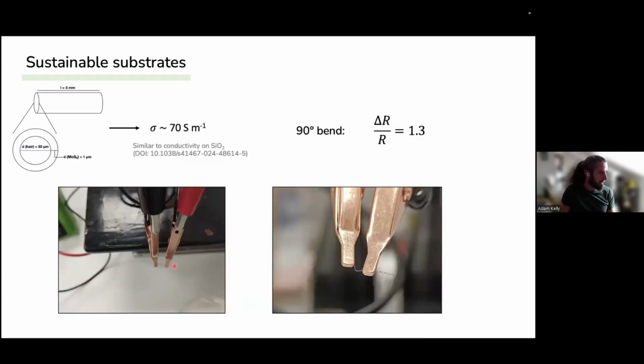So we coated one of these hairs. We calculated then the conductivity of the MoS2 along the hair, and it worked out at about 70 Siemens per meter. And this is almost exactly the same as the conductivity that we found for MoS2 on silicon dioxide. So it doesn't matter that we have this cylindrical structure of MoS2, we can achieve exactly the same conductivity. She managed to bend, almost by accident, the hair to a 90-degree angle, and this only resulted in an increase in the resistance of about a factor of 1.3.